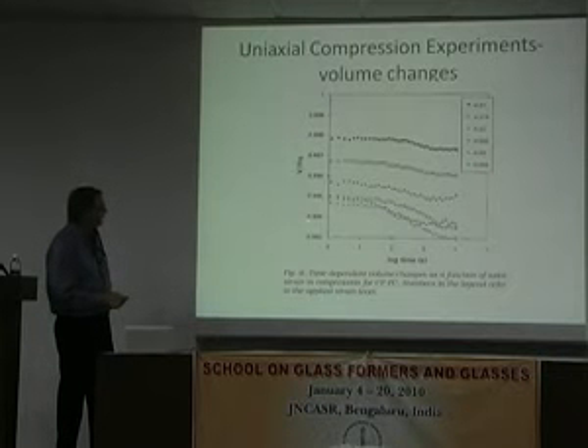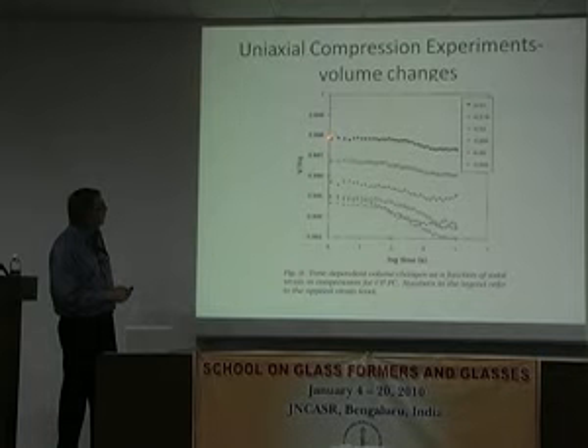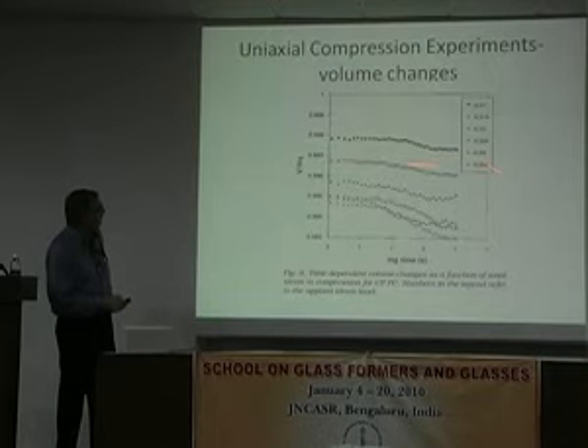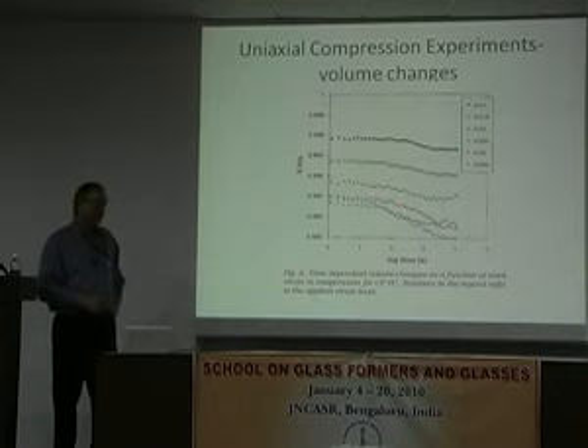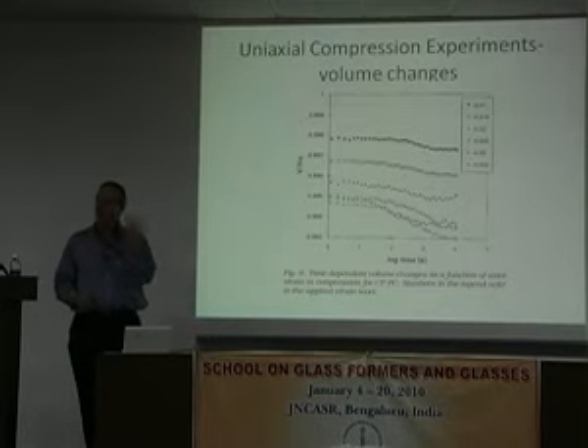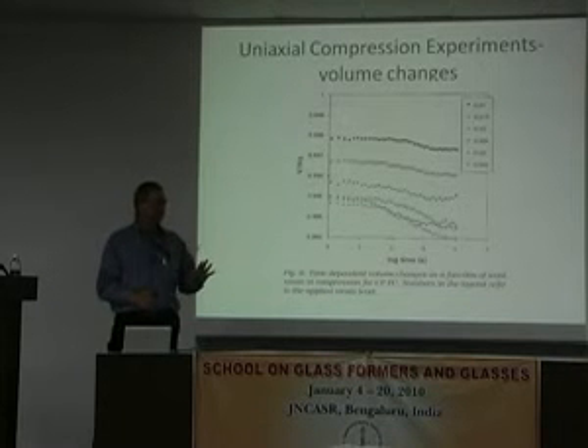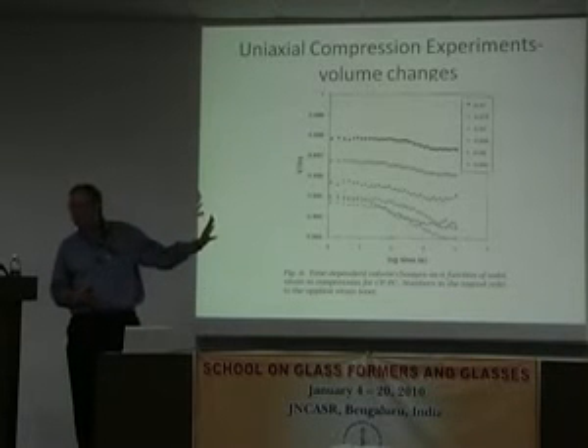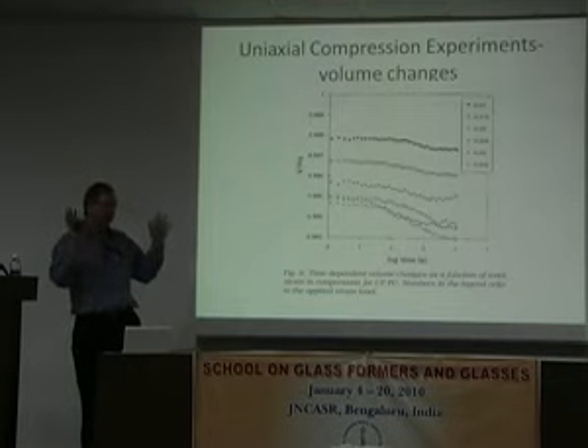But what we see is in compression, surprisingly, rather than relaxing back towards no volume change, in compression this material seems to want to get denser. Okay? And again, we don't understand that per se, but it's certainly not the usual type of behavior that people expect from these viscoelastic properties.